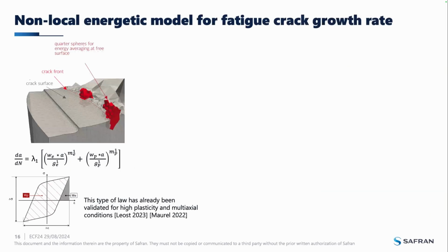In this condition of high plasticity, the delta K approach is not relevant. So I use a non-local energetic model, which is based on the partition of plastic and elastic energy. It is a non-local model because this energy is averaged in a specific volume at the crack tips, as you can see on the images in red. And for this law, there are 5 parameters: lambda, W for plastic, and W for elastic, and M for elastic and plastic. And here, a is the crack length. So this type of law has already been validated for high plasticity and multiaxiality in the literature.